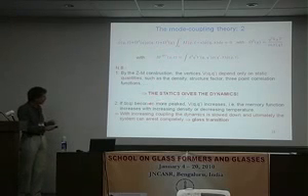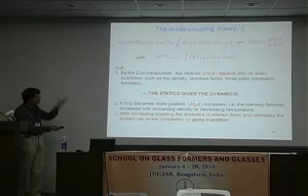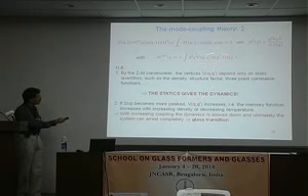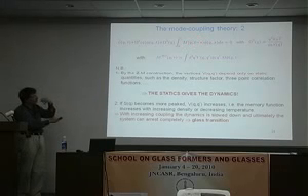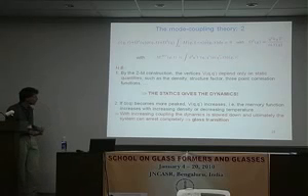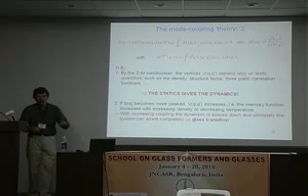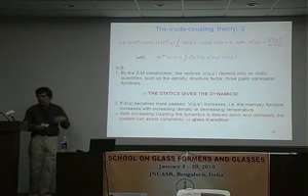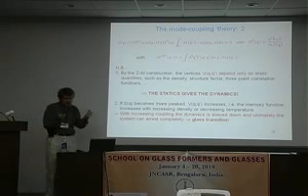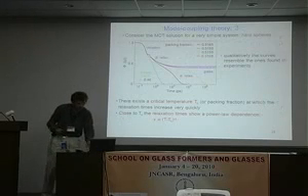My hand-waving feeling is that if the static structure factor becomes more peaked, then this vertex increases, the M increases, the feedback becomes stronger, and therefore the dynamics slows down with decreasing temperature. If this feedback mechanism is sufficiently strong, the system will completely arrest and you have the glass transition. So that's, in a nutshell, what mode coupling theory is about. And the other speakers will tell about the details.